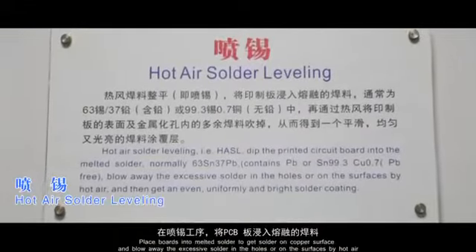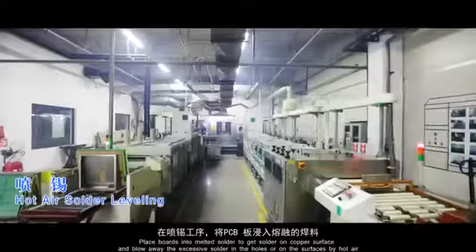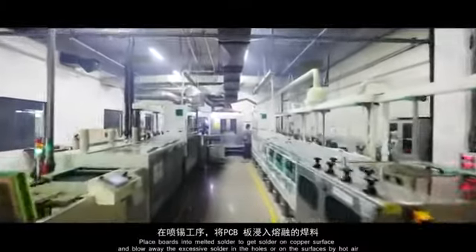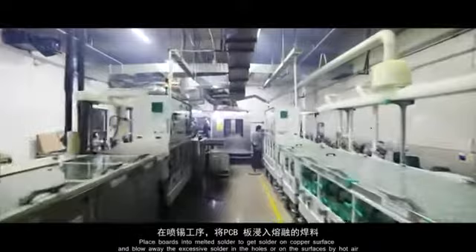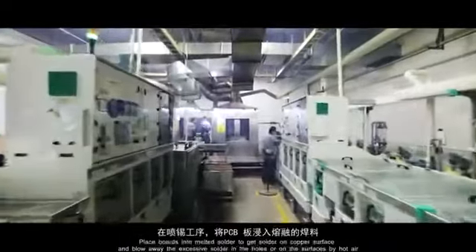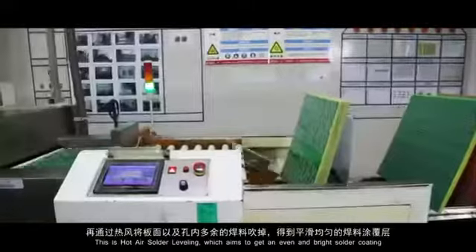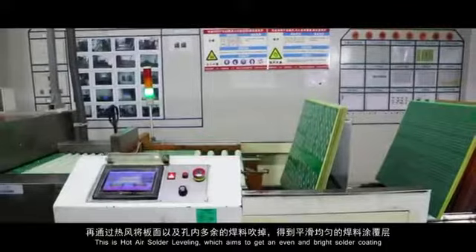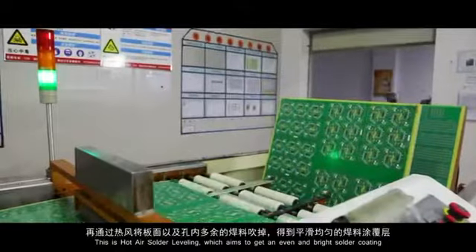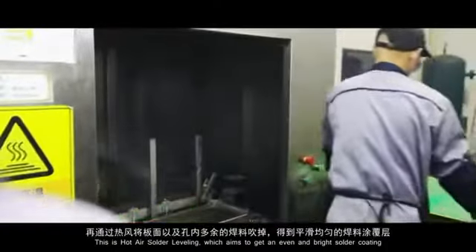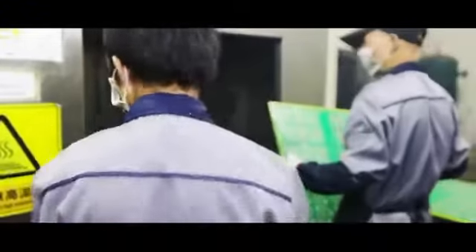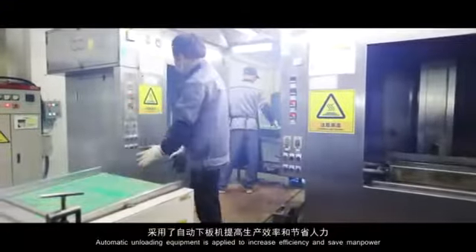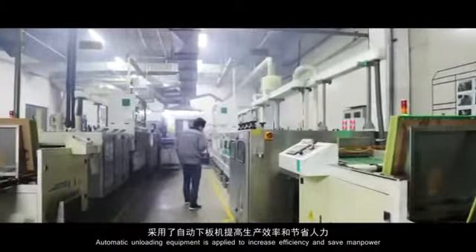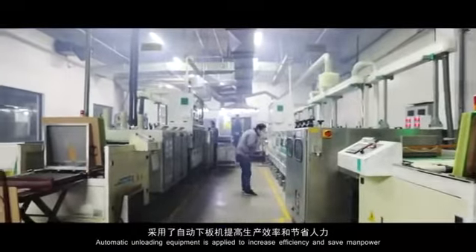Place boards into melted solder to get solder on the copper surface, and blow away the excessive solder in the holes or on the surfaces by hot air. This is hot air solder leveling, which aims to get an even and bright solder coating. Automatic unloading equipment is applied to increase efficiency and save manpower.